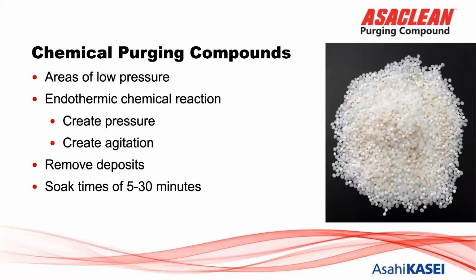And it helps, like I mentioned before, address cleaning in tough to clean areas: extrusion blow molding heads, extrusion dies, hot runner systems, or even an injection screw and barrel that might have some wear or some cracks and crevices, some valleys in there that we need to get into that a mechanical purge might otherwise have just walked right past. So a chemical grade is important for those types of applications and trouble areas. Soak times are around 5, 10, 15 minutes, 20 and 30 on a rare occasion, but depending on what temperature we're at, that will dictate how long the chemical reaction will go on for.